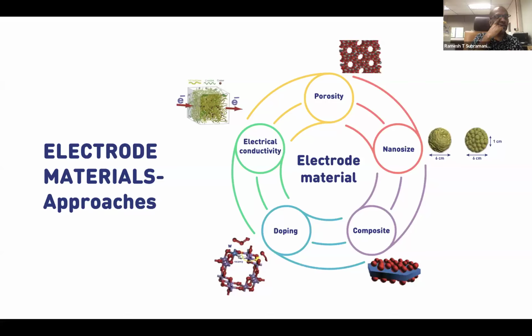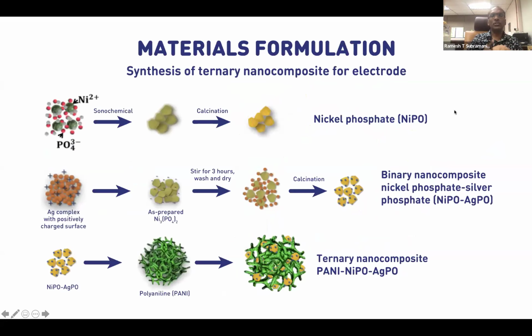Okay, next, let me go through some of the electrode materials. When we talk about electrode materials, we need to study porosity, conductivity, doping, composite, and nanosize. Here I'm going to share with you the ternary nanocomposite for electrode materials. The base will be nickel phosphate, then nickel phosphate and silver phosphate. And for the ternary, we add polyaniline, PANI, nickel phosphate, silver phosphate.